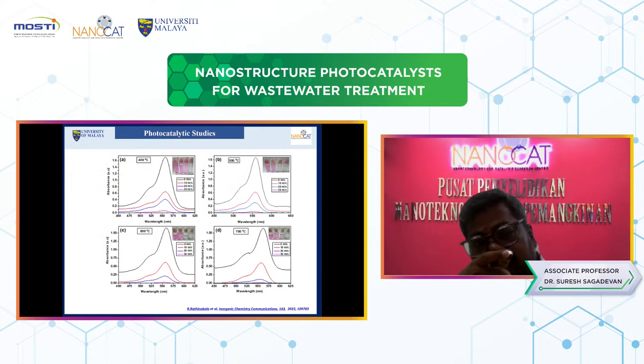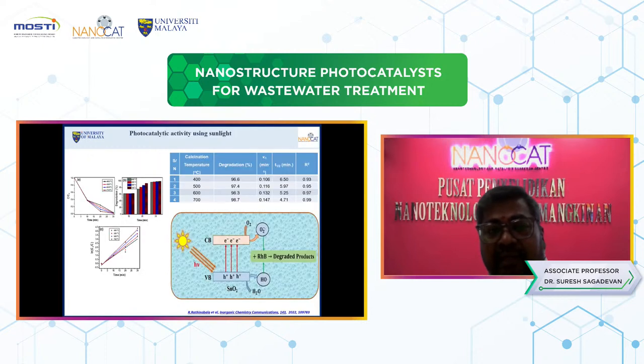And then we performed the photocatalytic studies by using sunlight as well as UV light. First, the photocatalytic UV absorption spectrum using sunlight. You can look at here, this dye was degraded very quickly, taking only 30 minutes. At 700 degrees Celsius, the maximum dye degraded, almost 99%, compared with the other calcination temperatures, followed by 600, 500, and 400. This is for the calcination temperature with the dye degradation percentage.